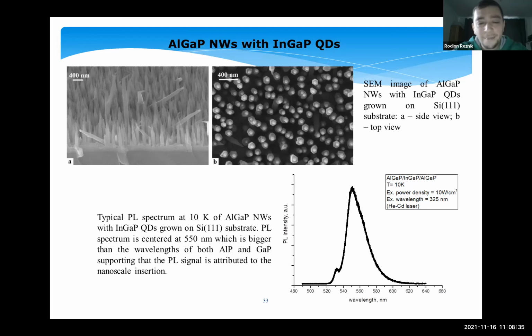But anyway, at low temperature we have photoluminescence from the quantum dots. It's from quantum dots for sure, because the 550 nanometers wavelength is longer than the wavelengths of both aluminium phosphide and gallium phosphide.